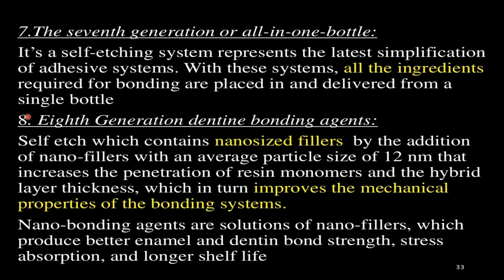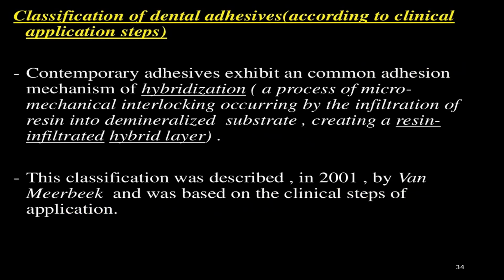Eighth generation dentin bonding agents are self-etch systems which contain nanosized fillers, with an average particle size of 12 nanometers, that increase the penetration of resin monomers and the hybrid layer thickness, which in turn improves the mechanical properties of the bonding systems. Nanobonding agents are solutions of nanofillers which produce better enamel and dentin bond strength, stress absorption, and longer shelf life.